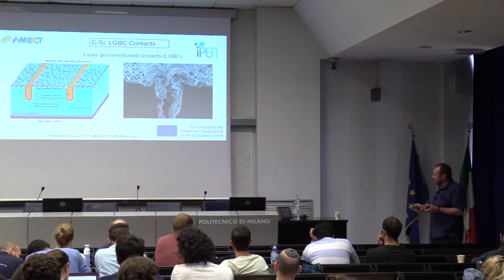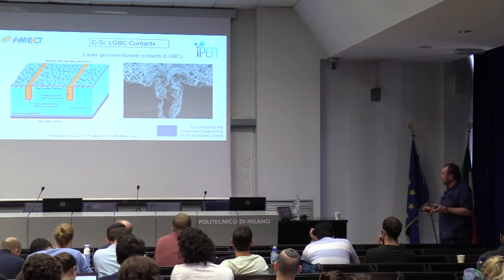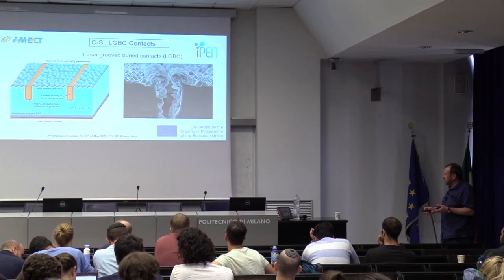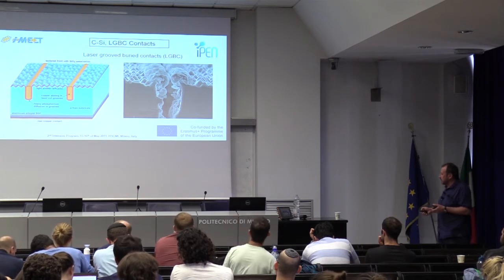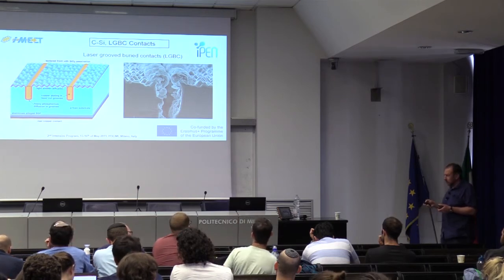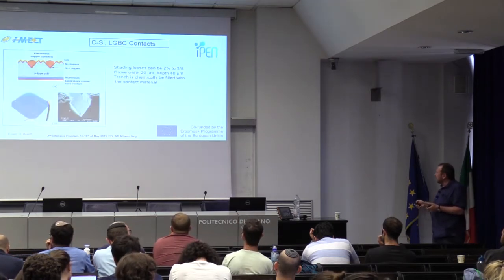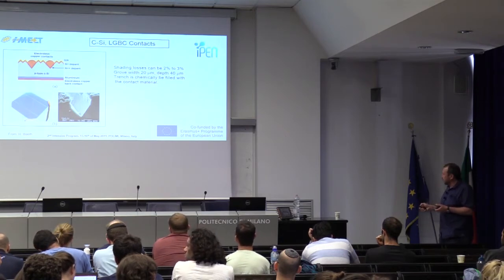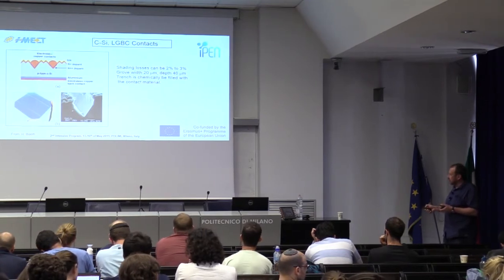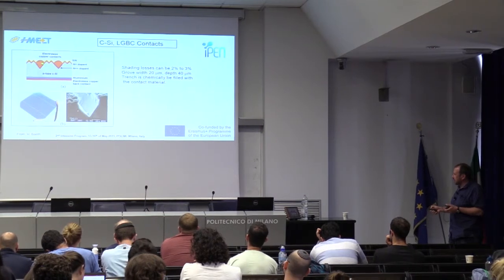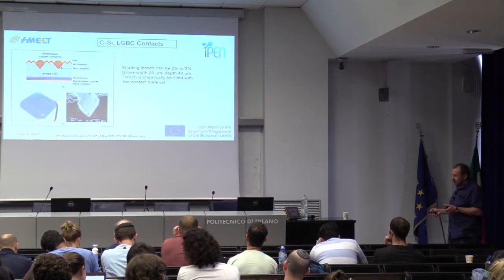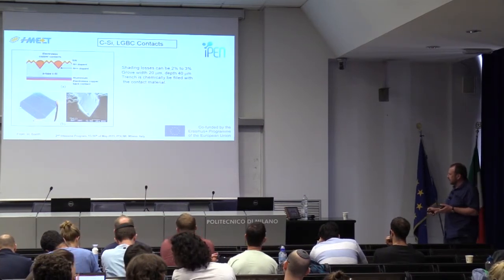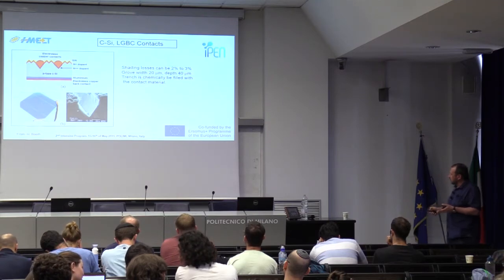The loss of area may be 2 or 3%, and you improve the contact between silicon and copper, and the copper itself has a good conductivity. So this is a similar groove, but with a different shape, also plated with copper, and the solar cell which has been produced by a commercial company.